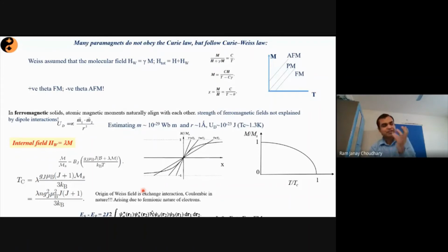Please remember that this internal energy, this exchange energy, is also competing with the thermal energy. When your thermal energy is high enough to overcome the exchange energy, then the thermal energy decouples the electrons which were interacting with each other earlier. When they decouple, they again become completely independent of each other and turn paramagnetic. But when your thermal energy is lower than the exchange energy, your system has some kind of magnetic ordering. That ordering we call either ferromagnetic or antiferromagnetic, depending on the sign of the exchange interaction. And the sign of exchange interaction depends on the material's property, the way those electrons are configured, right? So that is how we classify ferromagnetic, antiferromagnetic and paramagnetic materials.